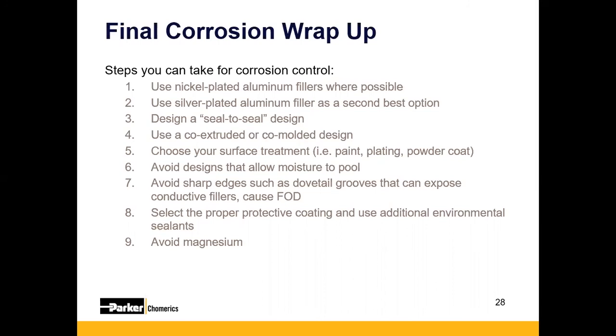We had a customer that had designed a magnesium box because they had serious weight concerns. They came in for an EMI gasket. We actually painted the housing with our CHO-SHIELD 2000 series. And when we put it into the salt fog chamber, we didn't realize that there were pinholes in the paint. And so when the housing came out of the salt fog chamber, it was literally a shell of 2000 series paint. The magnesium completely disintegrated. So just avoid the M word.